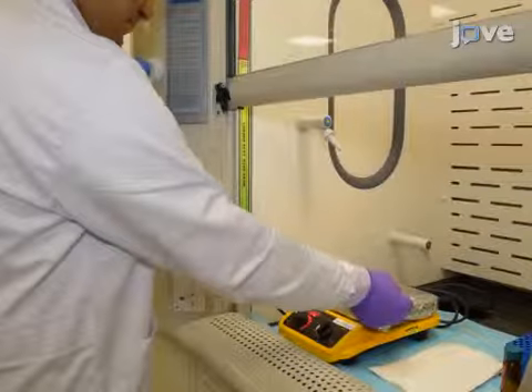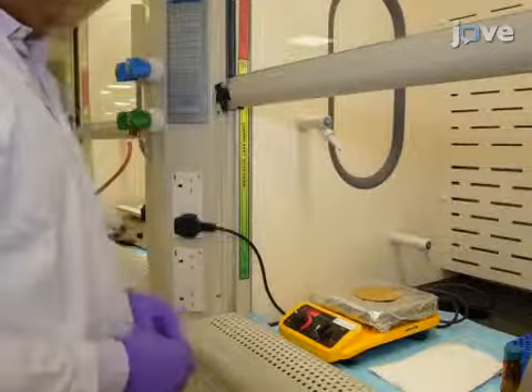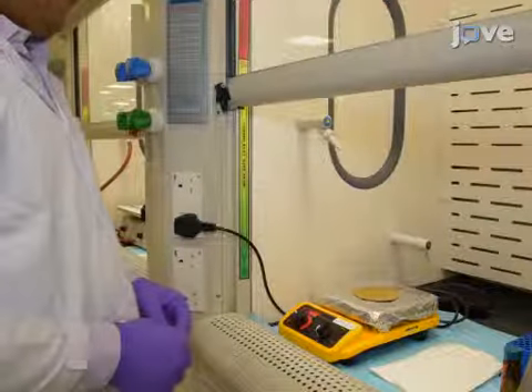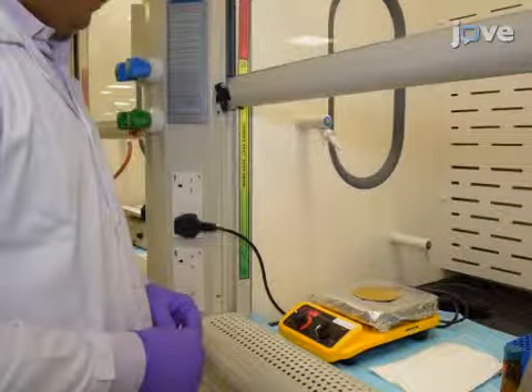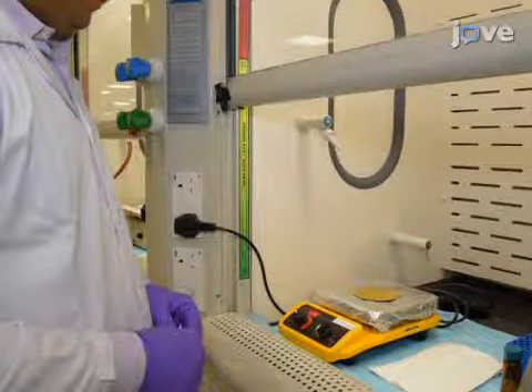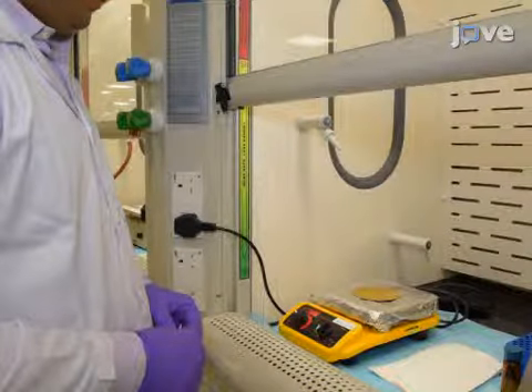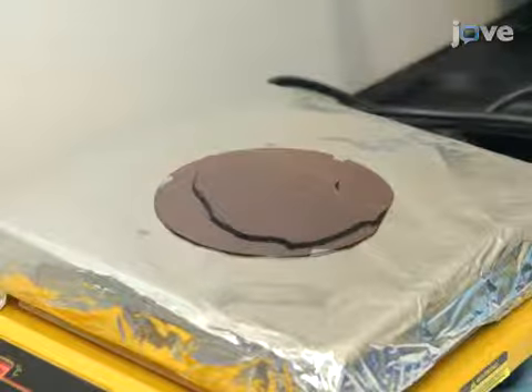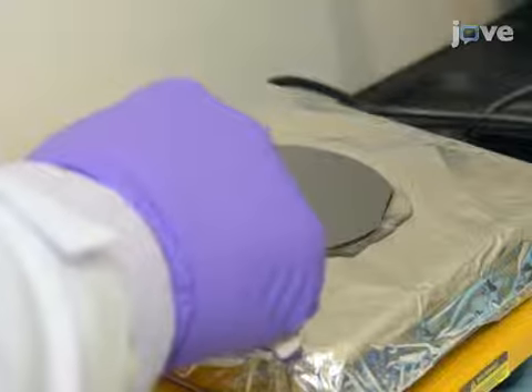Place the etched glass wafer on a hot plate at 110 degrees Celsius and melt wax on the opposite side of the glass wafer so that the entire surface of the wafer is covered with wax. Temporarily bond the glass wafer to a dummy silicon wafer by placing a silicon wafer in contact with the glass wafer and pressing firmly to remove the excess wax.